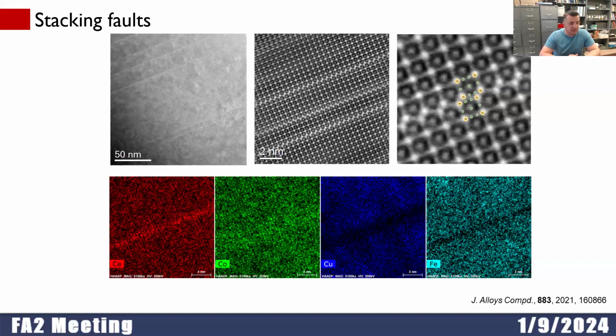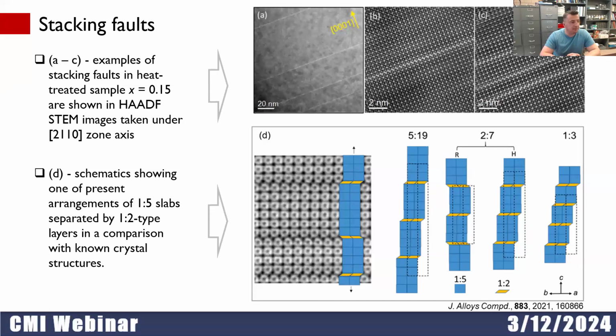This secondary phase was distributed uniformly, but not regularly. And obviously, this secondary phase was responsible for the appearance of coercivity. So when we compared it to similar structures, we saw that this is not very unusual. There are many cases where you have a combination of the matrix and stacking faults. Those stacking faults basically are inclusions of 1,2 type fragments into the matrix. But as I said, in our case, it's an irregular but uniform distribution of those stacking faults.